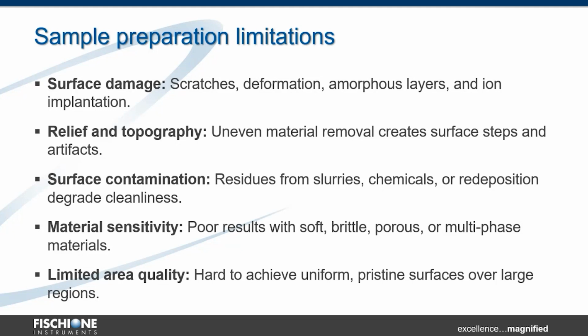As with any technique, sample preparation techniques have limitations. The first is surface damage. You can very easily introduce scratches, dislocations, create an amorphous layer, or ion implantation that alter the native material microstructure. Differential material removal between different phases causes topography or relief, making high-resolution analysis difficult. Sample preparation induced artifacts can obscure or mask critical microstructure details, compromising data and interpretation. Material sensitivity is also a problem. We often struggle with soft, porous, or multiphase materials, and those which are beam sensitive. And achieving a large, uniform, and pristine surface is often difficult using conventional methods.